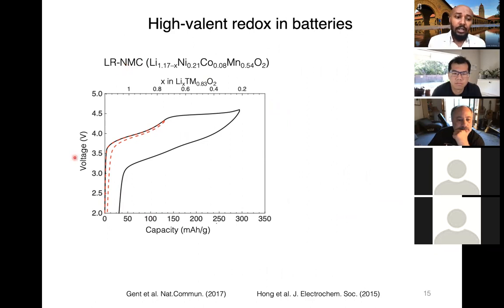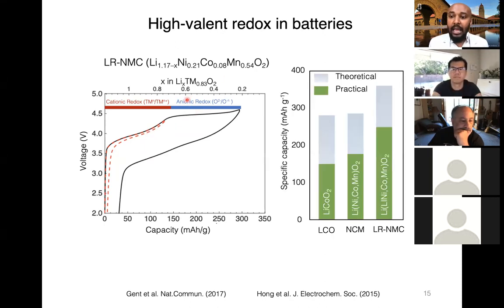If you look at the voltage capacity curve of this material, there are two steps. The first one is a cationic redox, and the second one is this anionic redox. And this black curve for lithium-rich NMC is very different from the dotted red curve, which I'm showing for lithium cobalt oxide, which we currently use in our batteries. And if you compare the red one and the black one, there are two major differences. The first one is, in the black one, since we have anionic redox, the amount of charge or capacity we can store is higher than the lithium cobalt oxide. Therefore, this anionic redox is allowing us to store more capacity compared to lithium cobalt oxide, which we use currently.